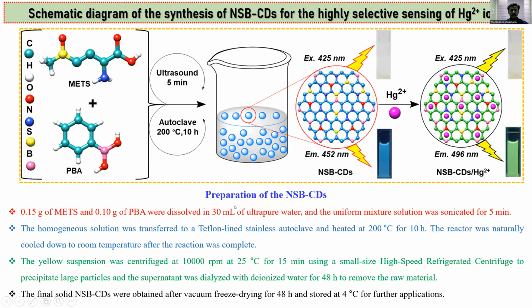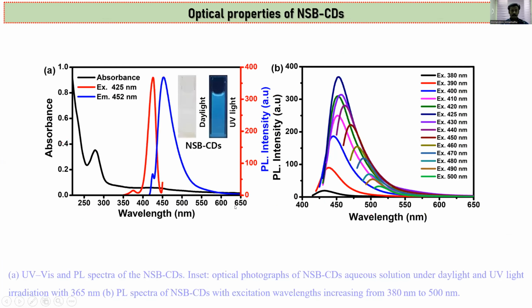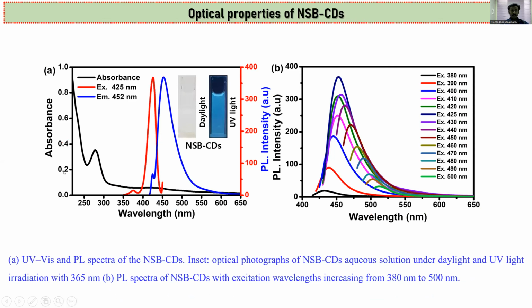For the optical properties, as I mentioned previously, the absorbance value we can get is at 425 nanometer, and the emission is at 450. This is a very small Stokes shift. We can confirm that 278 nanometer is the pi-to-pi star transition, and there was also a broad absorption peak at 425 nanometer, due to surface state defects of nitrogen and sulfur, importantly co-doped with boron. The maximum excitation and emission of these NSB carbon dots were observed at 425 nanometer and 452 nanometer.